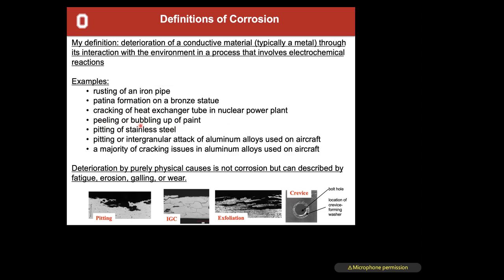Anytime you see peeling or bubbling up of paint, typically that is due to corrosion happening underneath the surface and the subsequent reactions that release gas that causes that paint to bubble up. If you ever have your stainless steel utensils and they have little black dots on them, a lot of times that's due to pitting. So you're getting contamination or pitting resulting from just basically the contamination that's in everyday air. It might be contamination from your cleaning products, but pitting of stainless steel has these little black dots all over it.